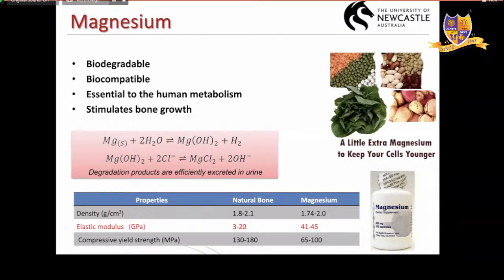What I mean is, you can't overdose yourself with high magnesium, because if you look at the mechanism of magnesium dissolution here, magnesium reacts in water. Basically, body fluid has a lot of water in it. That's how it reacts. It forms magnesium hydroxide, and the magnesium hydroxide, in the presence of chloride ions, which body fluid has, forms magnesium chloride, which is soluble in aqueous solution. So there is no accumulation of magnesium in the body. Even if you overdose, it's easily excreted. That's the reason why you have dietary magnesium available in supermarkets for treating cramps and sleeping disorders.